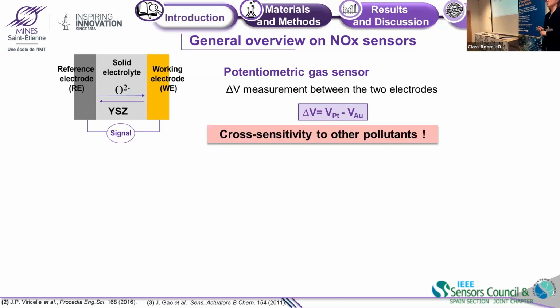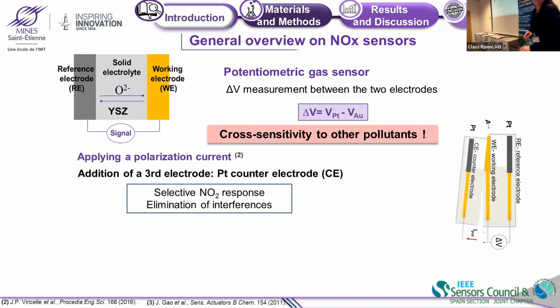The main problem of this kind of sensor, as with many gas sensors, is the cross sensitivity to other pollutants. In order to solve this problem, we chose 2 approaches. First, we apply a polarization current with the addition of a 3rd electrode in platinum that we call the counter electrode. This allows us to get a selective NO2 response by polarizing the working electrode negatively, and eliminates some interference.